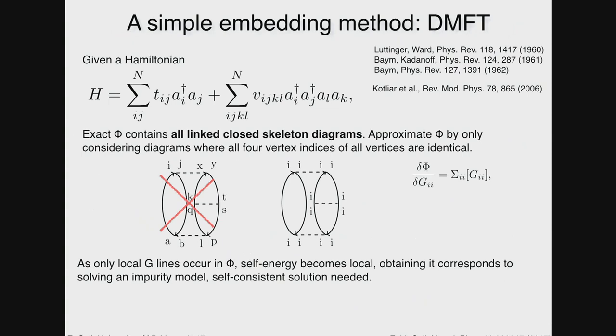Now, there's a very simple embedding method, or a first simple embedding method, the dynamical mean field theory. Right? Dynamical mean field theory is an approximation to that Luttinger-Ward functional where you take the exact Luttinger-Ward functional and you kick out all of the terms that don't have the same vertex index at every single vertex, or the same orbital index at all of these places. As you have only G_ii in here, when you take the derivative with respect to G, your self-energy only is sigma_ii, and with that, your self-energy is purely local to your orbital.